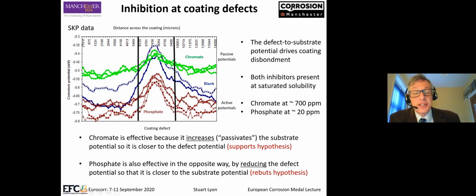So chromate is present in this case at about 700 ppm in the leachate under saturated solubility. We used an alternative inhibitor, which was found to be relatively effective, not as good as chromate, but relatively effective. And that's present at about 20 ppm in the saturated state. And what that did, instead of altering the substrate potential, raising it, it reduced the defect potential. Not quite as well. You can still see there's a bigger potential difference between the defect and the substrate, but that potential difference has dropped.